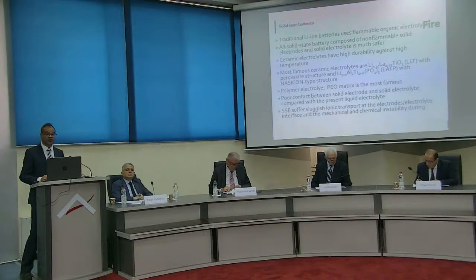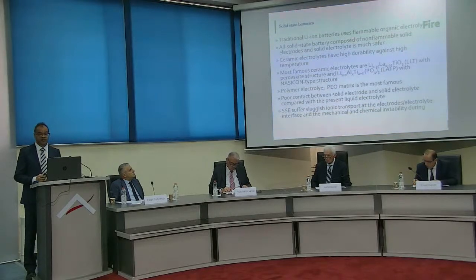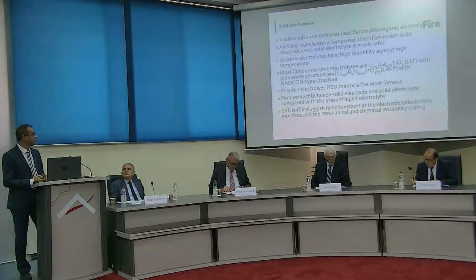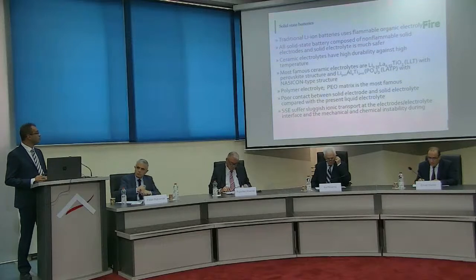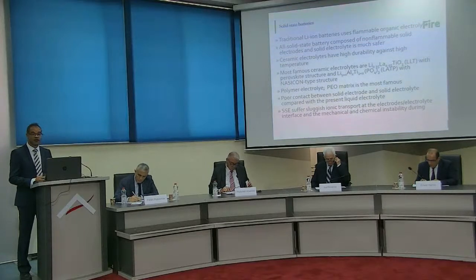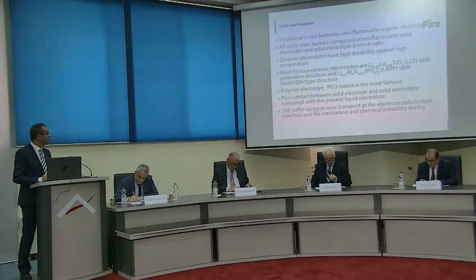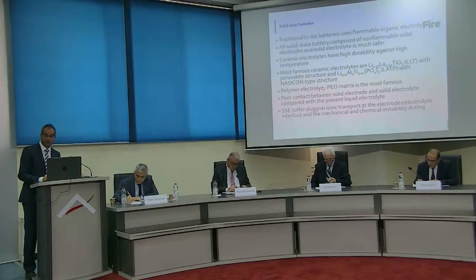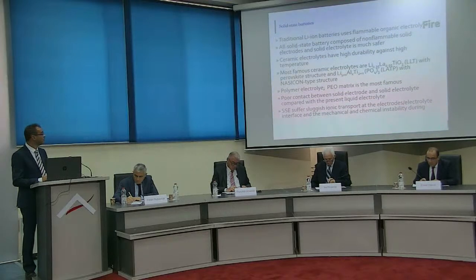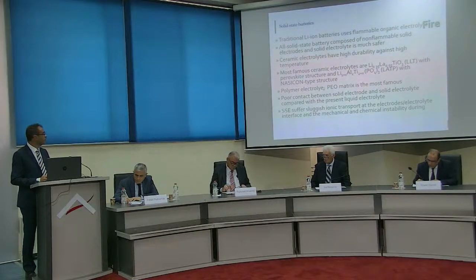So it's a mature industry, but when we adopt it in lithium solid-state batteries, we have so many technical problems, including, for example, the kinetics, or the sluggish movement of the ions, and also the problems at the interface between the electrode and the electrolyte. There are also polymer electrolytes, which usually use some sort of ionic conductive polymers. And this one again has the same problems at the interface between the electrode and the electrolyte, and also the transport of the ions inside the electrolyte itself.